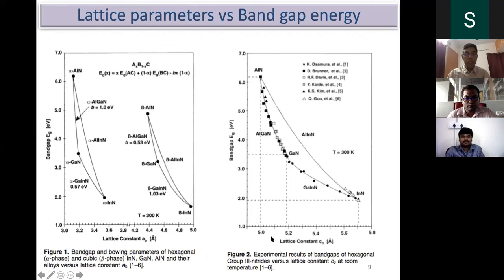See, this is the A-axis, this is the C-axis. When you see the A-axis, aluminum nitride and gallium nitride are very close to each other. So the growth of gallium nitride over an aluminum nitride substrate is very easy. That's what we have to understand from this system. And this alpha gallium nitride, alpha aluminum nitride is used in the case of LEDs. Similarly, you can see aluminum nitride versus gallium nitride in the case of the C-axis, but there is a gap, not like the A-axis, but you can see a variety of alloys are grown, and they are studied in laboratories all over the world.